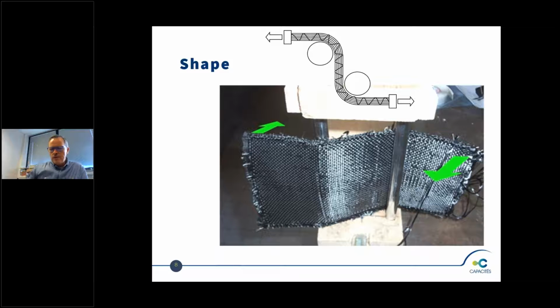First of all, the 3D interlock preform is quite difficult to shape because all these plies are just maintained together by means of the interlock yarn. And if you want to make something other than a flat surface, then you have to force the plies to slide onto each other in order to avoid wrinkles. Otherwise, if you have a wrinkle on the ply, it means that at that location, the ply has no more strength. And it can be a nightmare to invest so much in carbon parts and to miss the shaping of the material. It's one of the issues which will be at stake for any industry trying to use this material to do other things than flat panels.